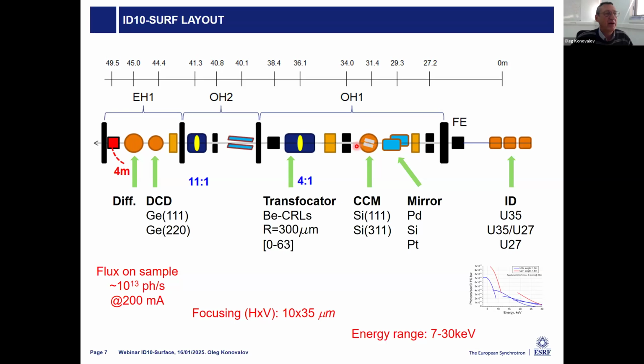And when the beam is already monochromatized, we can focus it on the sample or on the detector. So it depends what we want, but usually we focus on the sample. And in this case, we use the transfocator. This is beryllium compound refractive lenses with a radius of 300 microns. And then we can set from 0 to 63 lenses. And like this, we can focus each energy at which we work, or any energy, on the sample with a 35 micron beam vertically and 10 horizontally.